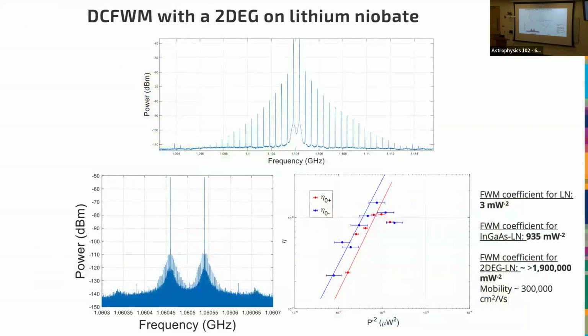And here we find, again, so we had 3 for lithium niobate alone. We put our room temperature semiconductor down, we get a factor of 300 increase. We're almost at about a factor of 1,000,000 larger compared to lithium niobate alone for this 2D electron gas. So in fact, it makes the experiment difficult to do, because almost any amount of RF power that you put in will produce this Kerr comb.